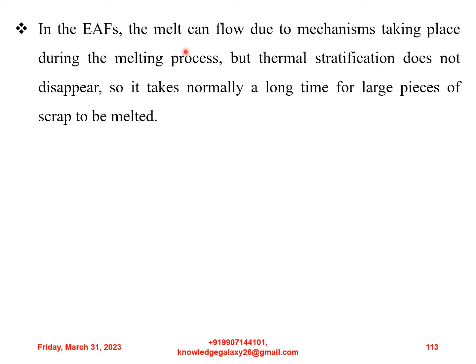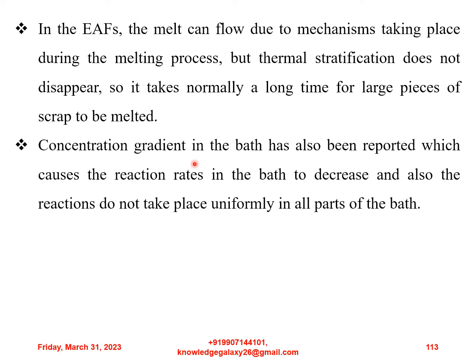In the EAF, the melt can flow due to mechanisms taking place during the melting process, but thermal stratification does not disappear. So it normally takes a long time for large pieces of scrap to be melted. Concentration gradients in the bath have also been reported, which cause the reaction rates in the bath to decrease, and also the reactions do not take place uniformly in all parts of the bath.